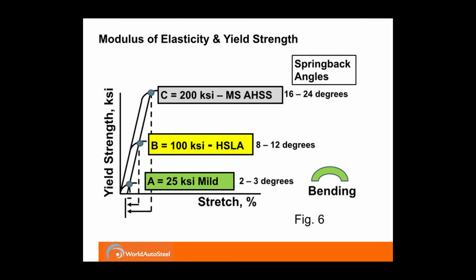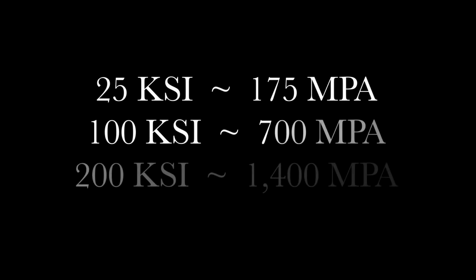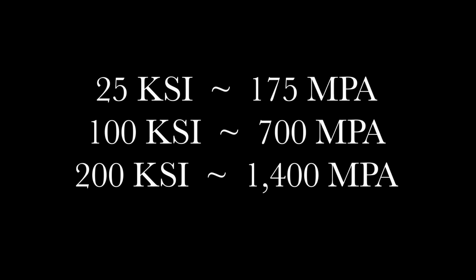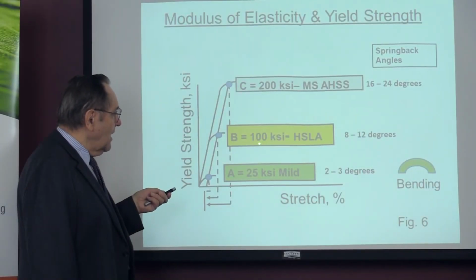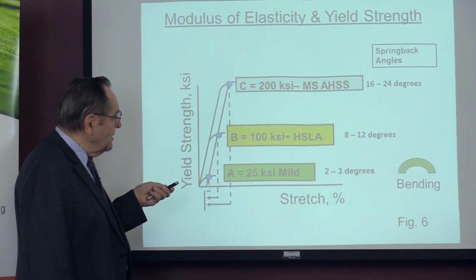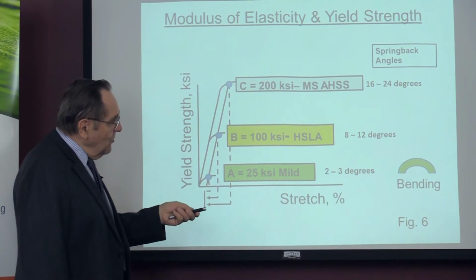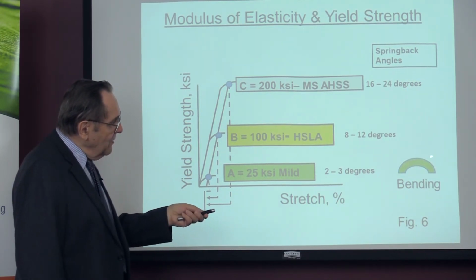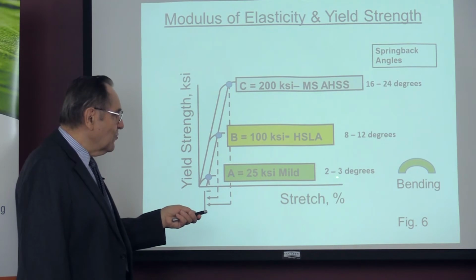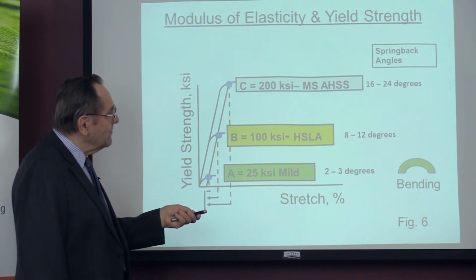Now, before the advanced high-strength steels, we had 25 KSI, which in this case would be an AKDQ steel, or a mild steel, which is the global definition. This is the high-strength low alloy steels, 100 KSI. You have 4 times the amount of springback. So if you're making a bend over here, you had made 2 to 3 degrees of bend springback. Now you're talking 8 to 12.